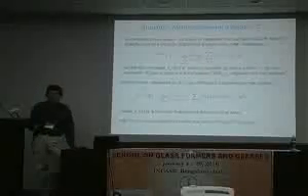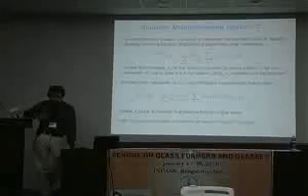Okay. The Q dependence in X-ray comes from the extended charge distribution, which goes into the form factor. Because you have a charge distribution, if you do a Fourier transform, you will also get a Q dependence. Whereas, as he mentioned correctly, nuclear scattering is effectively a point object, so you don't have the Q dependence in that.